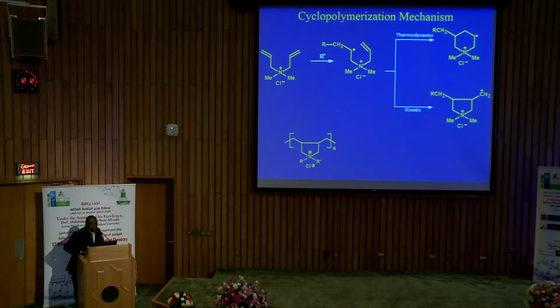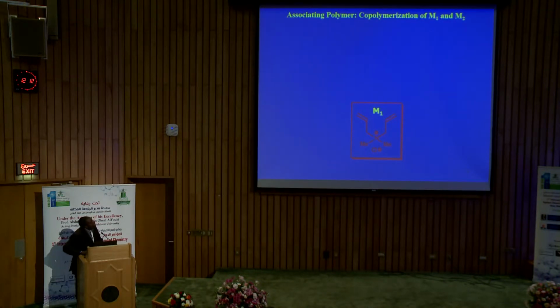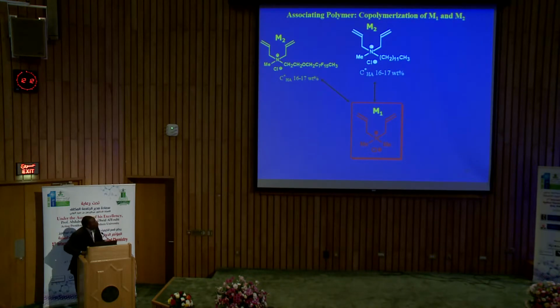With different R groups were synthesized, and sometimes these polymers were copolymerized with sulfur dioxide to form a copolymer. Sometimes a group of scientists also tried to copolymerize these monomers, which I call monomer 1, with a hydrophobic monomer. Here, they got a critical hydrophobic association concentration at 16 to 17% of the polymer, which is too much compared to the acrylamide system. The second group also attempted to use that particular monomer and got almost the same thing, 16 to 17. Another group copolymerized M1 with M2 at 5 to 30 mole percent, and they discovered that it leads to a polymer with intramolecular association.